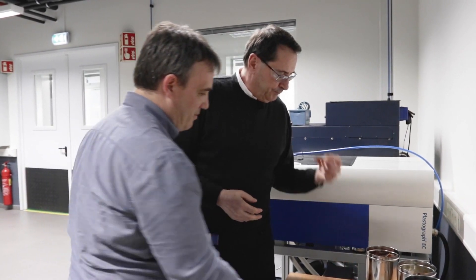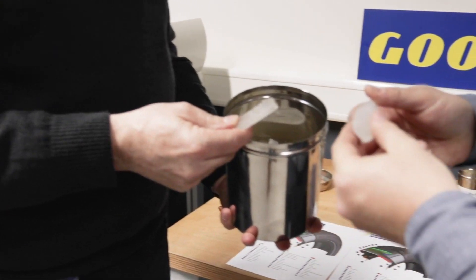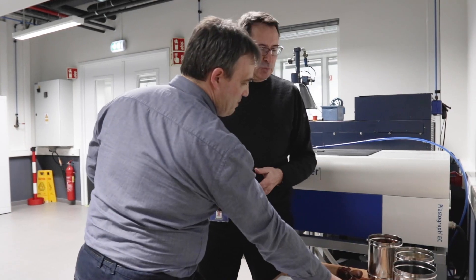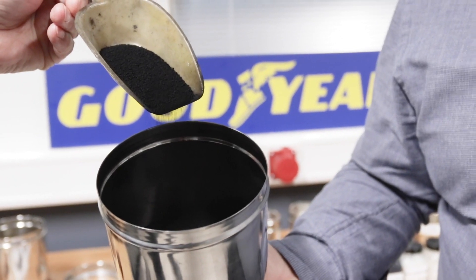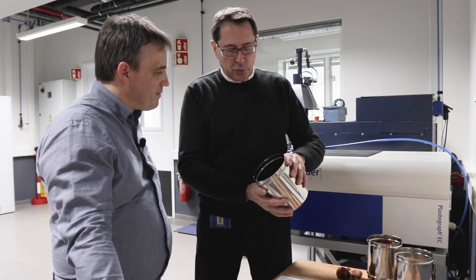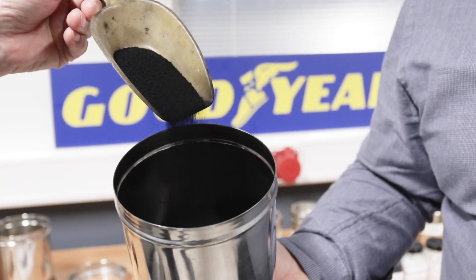We have natural rubber and we also have synthetic polymers — this one here. You can see it's quite different; it's coming from crude oil and there's a whole process to come to this product. It could also be another color — that's just one type. We have a lot of types of synthetic polymers, but this one is white. Then you have to imagine it's like spaghetti — polymer strands. We have to put something in between, and one of those materials is a filler: a carbon black filler. You should not touch this one because it also comes from crude oil — you burn the oil and the end product is the carbon black that we put into our mix.